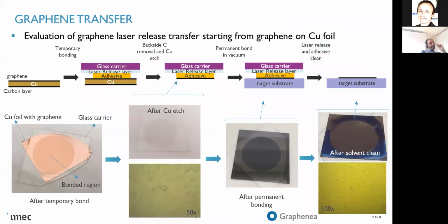Okay, and we can do that also, with a similar sequence, for graphene, because it's more difficult to release the graphene mechanically from the copper substrate. Here we are etching away the copper substrate, but nevertheless, it proves that you can use the same method for graphene.